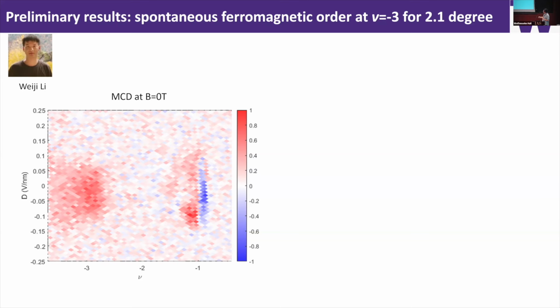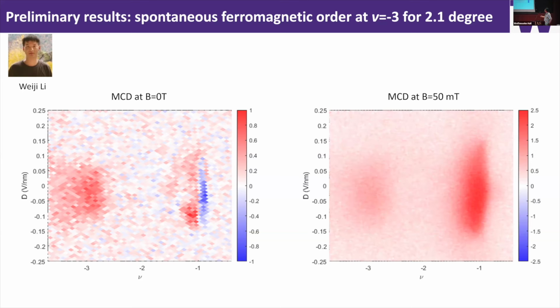The data is taken at zero magnetic field. So this data clearly shows that there is a ferromagnetic order, and actually in a large phase space around filling factor -3, so it's robust. The data also shows that there's a significant spin fluctuation in the system as we tune the carrier density. So we can suppress this spin fluctuation by doing the measurements again at 50 millitesla. Now you can see the data is much smoother, but it doesn't change the conclusion. There's ferromagnetism at the filling factor -3 for the twist angle 2.1 degree.